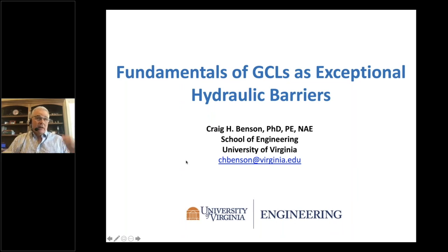That's good practice. In fact, I have a case history. One of my students, Thomas Williams from SCS, reminded me that I owe him to get his paper finished, where we worked on a site where a GCL was not covered, and it had sat exposed for a number of years, severely damaged. Now, that's an extreme case. It had just a geomembrane on top, but no confining soil on top, and it was damaged beyond recognition. It was physically there, but its effectiveness as a barrier was completely lost. We put a lot of energy into installing these, so we want to protect them to make sure the product we put in is maintained.